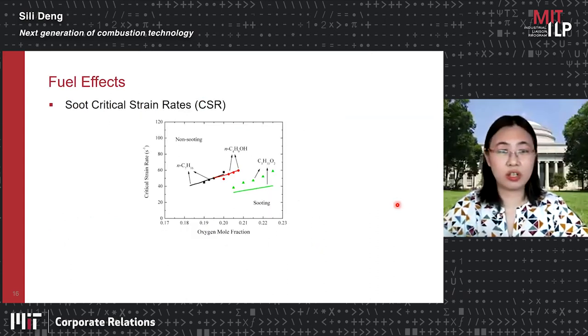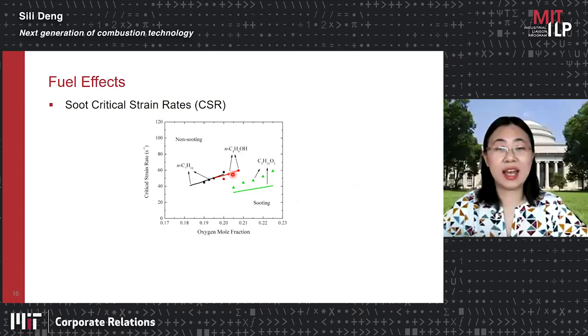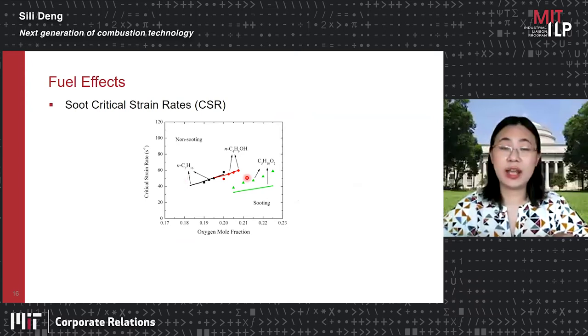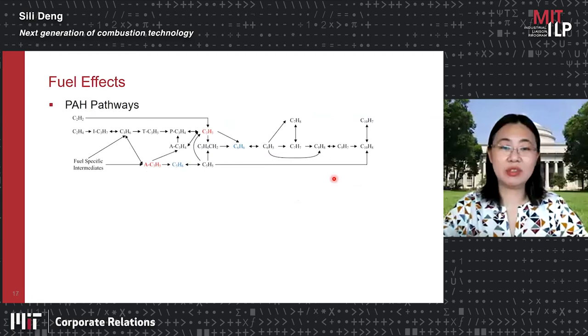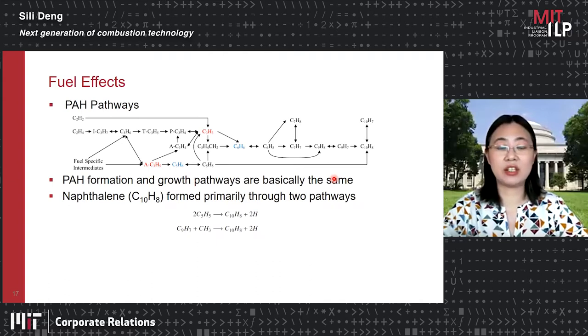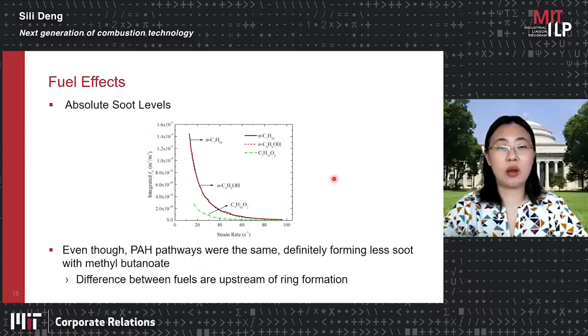So long story short, again, we see the fuel effect is that the biodiesel indeed is less likely to generate soot. However, the bioalcohol is just as sooting as the traditional diesel. So we are interested to see why this is the case. By analyzing the chemistry, the conclusion we have is that the PAH formation and growth pathways are basically the same, no matter what kind of oxygenated groups you have. So our attention goes to what happens to the upstream chemistry pathways.